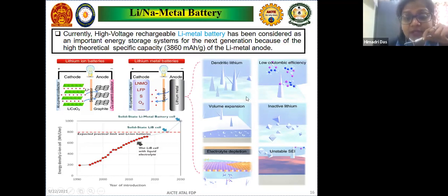So people have focused on lithium metal batteries, but when we use lithium metal as anode, there are also many issues like lithium dendrite formation and low coulombic efficiency, because whenever dendrite formation or other degradation of the anode happens, coulombic efficiency reduces. Similarly, when volume expansion happens, lithium dendrites form very easily, and it gives a short circuit. And the most critical fact is that when we are using lithium metal, the lithium is sufficient, but with gradual charge discharge, dead lithium is created. What is dead lithium? Dead lithium is nothing but inactive lithium. Some of the lithium gets charged and discharged, and then it cannot return to its original position. So those lithiums are really inactive, and again we face insufficiency of lithium in the lithium metal battery.